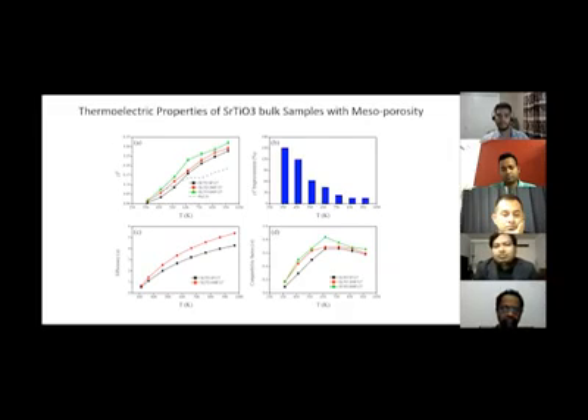Some people have got like 0.4 or something maybe. So our result is also good, comparable to other groups. So this is actually my first work. I have done 2 more works, one in strontium titanate, another one in barium titanate, and try to improve the ZT by reducing the main thing, which is reducing the phonon thermal conductivity.